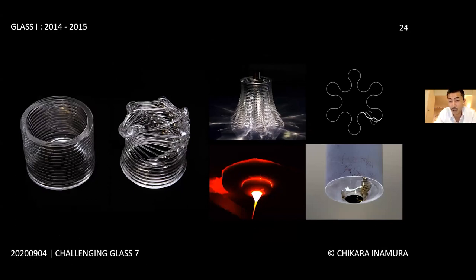Interesting phenomena were observed during this research. These two products on the left were printed in the exact same parameters. One is continuous and the other shows a distinct spiral pattern. Closer observation of the bottom face of the nozzle revealed an asymmetric adhesion of glass. Molten glass is extremely viscous, and this asymmetric adhesion at the nozzle causes an effective shear force to vary along the path and cause differential deposition.